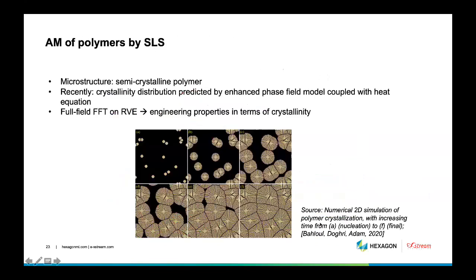Let me take the other example, which is microstructures created by additive manufacturing of polymers by SLS. I showed an animation earlier where we start by putting a certain number of nuclei in a representative volume element, and then the phase field model and the heat equation model coupled together act and are able to predict the spherulite creation over time.